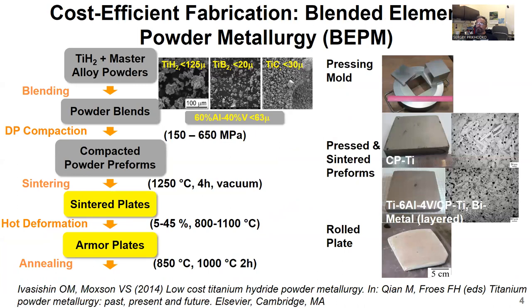Our strategy for cost-efficient fabrication of titanium armor is to sidestep conventional and pricey ingot metallurgy. The suggested approach is based on use of blended elemental powder metallurgy of hydrogenated titanium. Powder metallurgy is cost efficient. Besides, you can make laminates that combine layers with different properties, say high strength or high ductility, generally not compatible in one material. The major drawback is possible lowering of performance due to densification problems.